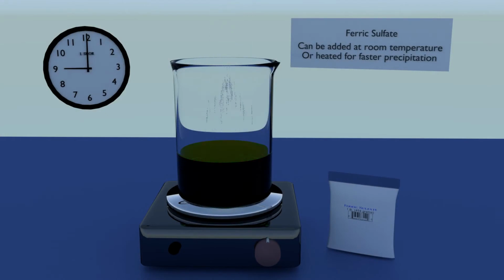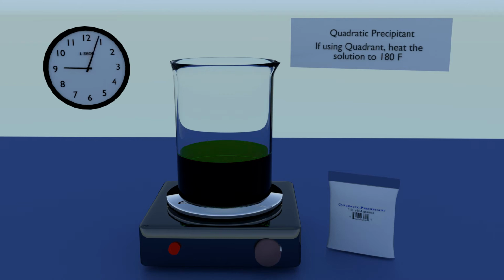Ferric sulfate. This is an odorless precipitant that can be employed at room temperature. Or the solution can be heated for more rapid precipitation. Quadratic precipitant. This is an odorless precipitant. It creates large, heavy gold particles. The solution should be heated to 180 degrees Fahrenheit for 30 to 60 minutes.